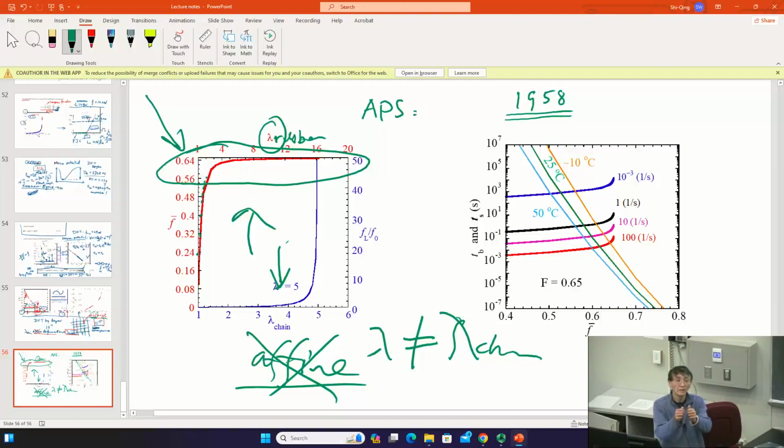So room temperature, again, let's say I use 10 seconds. Stretch there and break. Make your numbers. Let's say I stretch 3 times, it breaks. Lower the temperature. Let's say you do it at 0 degrees, or even minus 10, still way above Tg. You'll find your rubber stretches much more.